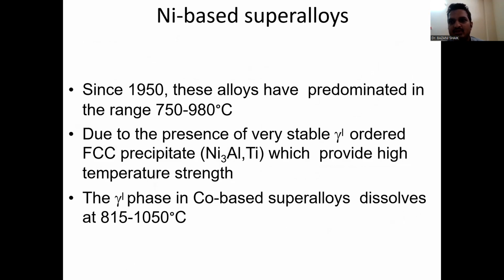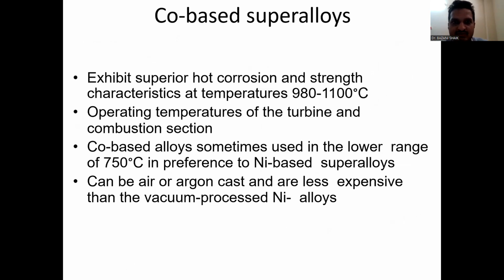When we are discussing the classifications of superalloys, the nickel-based superalloys are predominant in the range of 750 to 980 degrees centigrade due to the presence of the very stable ordered face-centered cubic gamma prime phase, nickel aluminum titanium, which provides high temperature strength. And here the gamma phase in cobalt-based superalloys dissolves at 815 to 1000 degrees centigrade. That shows a nickel base.